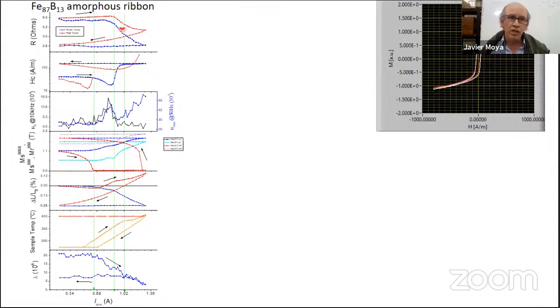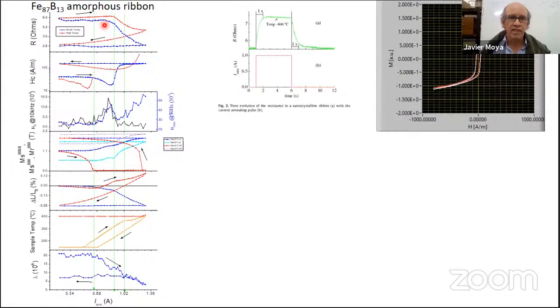So in only one figure, we have the measure of the electrical resistance at high temperature and at low temperature. How is it possible? Well, in this case, we hit the sample with a current pulse of about 6 seconds. Once the sample reaches the steady state in temperature, we measure the properties at high temperature, and then we allow the sample to go down to room temperature, and then we measure the room temperature properties.